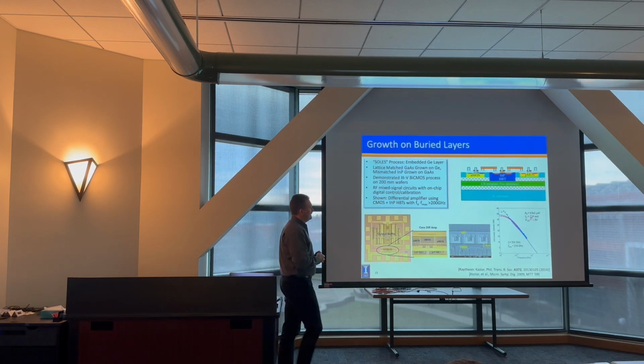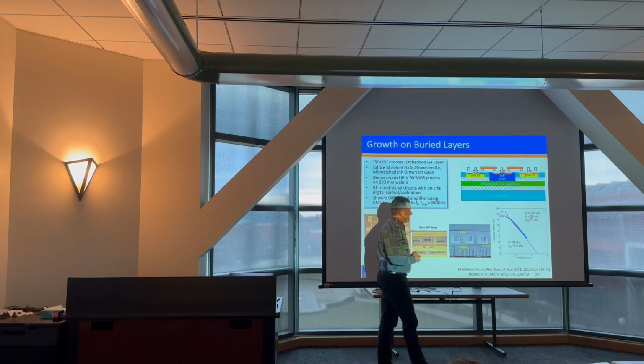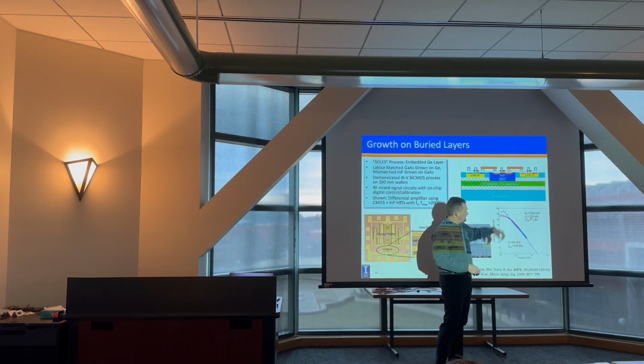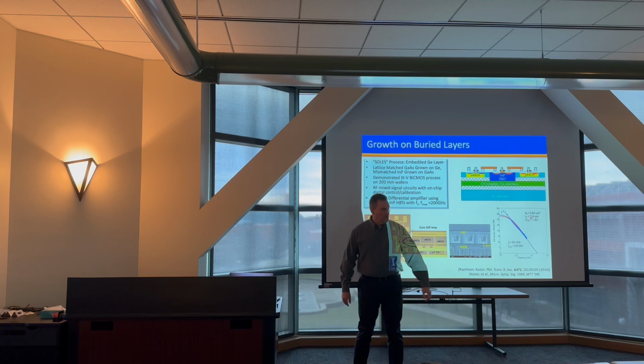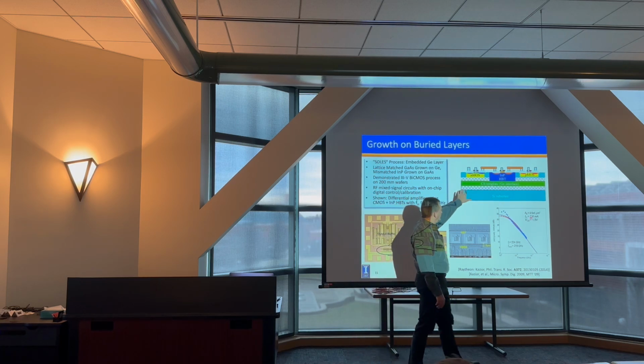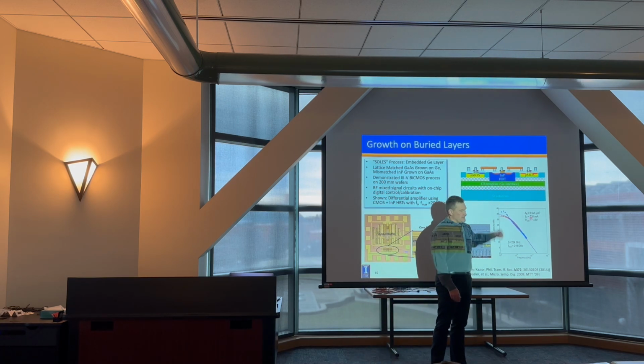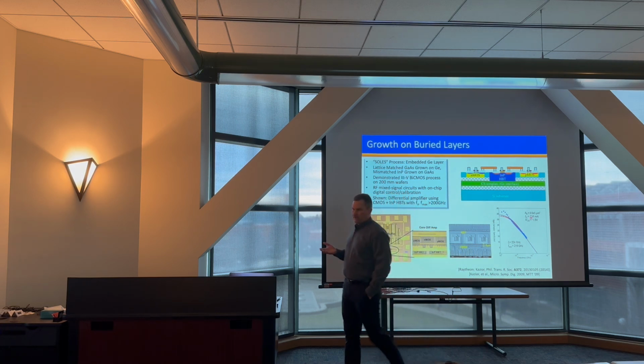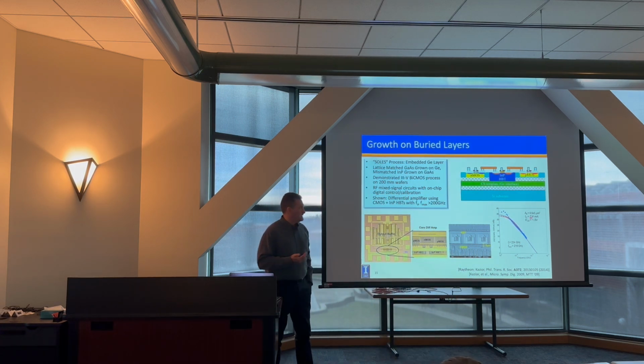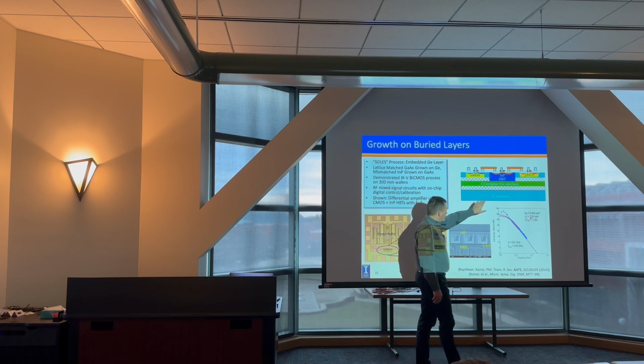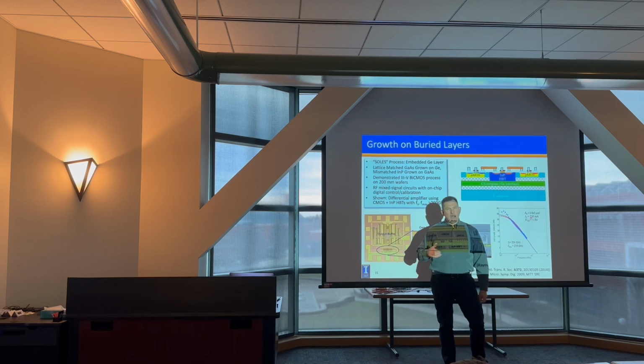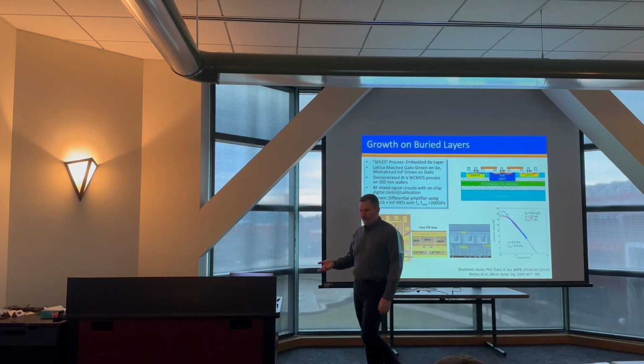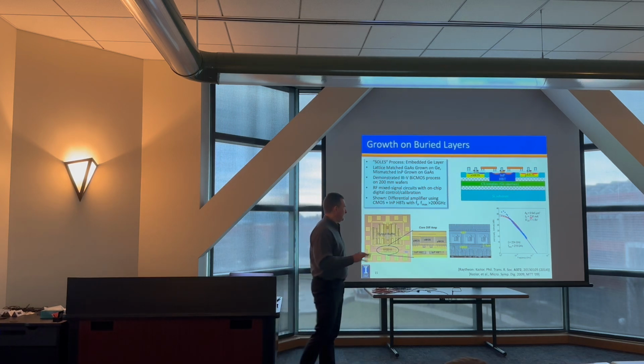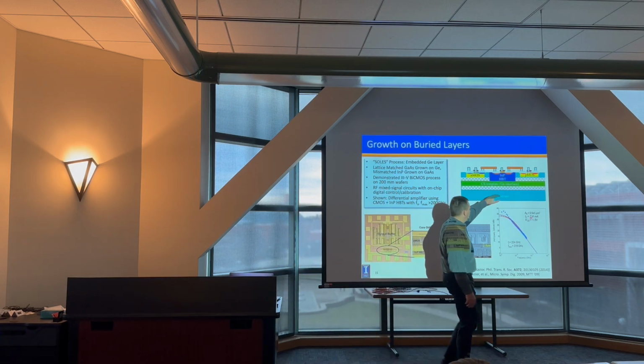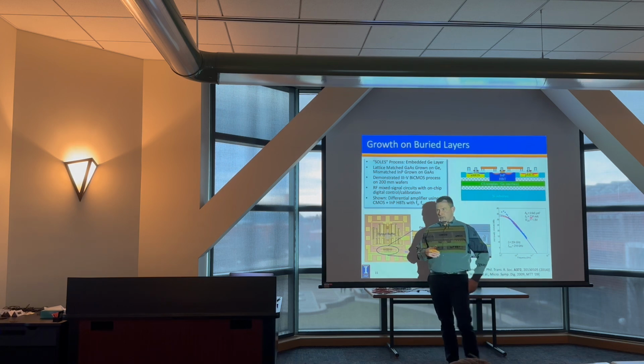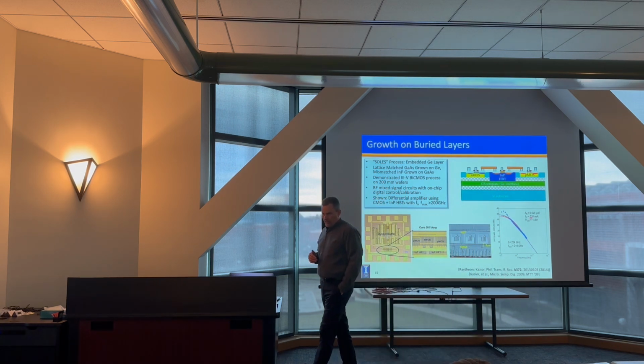There's been work using growth on buried layers. So an example here, you have a silicon substrate. You have something that they call the compound semiconductor template, which in this case is germanium. We know how to grow gallium arsenide on germanium, and we know how to grow indium phosphide on gallium arsenide. Again, there's defects involved, but you can basically do a multi-step growth process in order to get that.